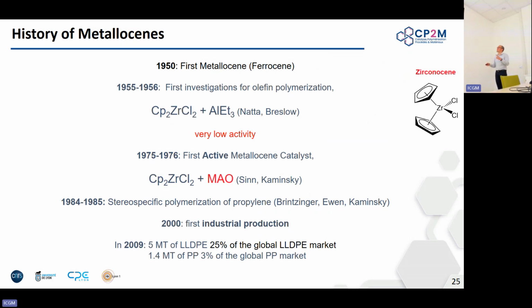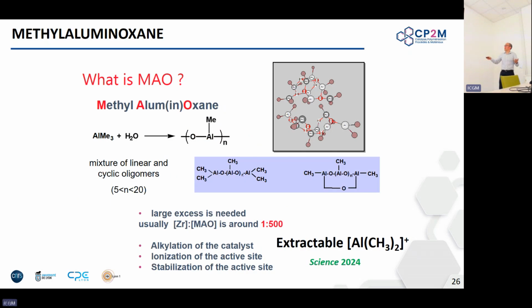Just a little bit of history on metallocenes. One key discovery was methylaluminoxane, MAO, okay, and this allows you to activate things such as zirconocenes or titanocenes, okay. So Cp2TiCl2 will alkylate, cationize with MAO, and this will give you the metal carbon bond and the open coordination site, because it will be a cation, okay. A comment about MAO, there is a fascinating article in Science this year about the extractable aluminum cation, okay, and this is supposed to be the one responsible for dealkylating and making the cationic titanium 4 type species.